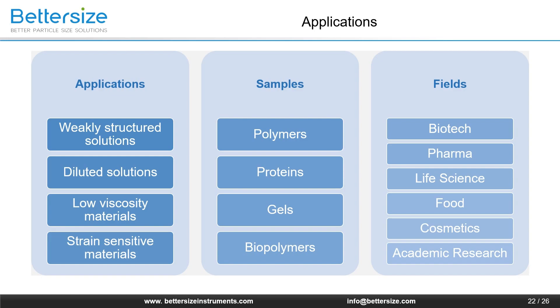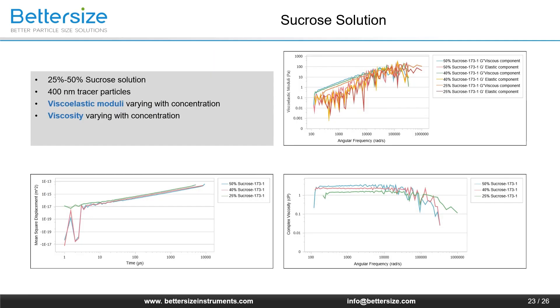Here are some examples of how B-nano DLS microrheology obtains rheological information. The first example is sucrose solutions prepared at concentrations of 25%, 40%, and 50%; 10 microliters of 400 nanometer negatively charged polystyrene spheres were added as tracer particles. The MSD curves show that higher sucrose concentrations result in lower MSD values and lower tracer particle velocities. The viscoelastic modulus curves showed strong viscosity across the concentration range and moduli increased with increasing concentration. From the complex viscosity versus frequency curves, at relatively low frequencies the complex viscosity did not change significantly with frequency, while at high frequencies it showed a downward trend, indicating weak shear thinning behavior.